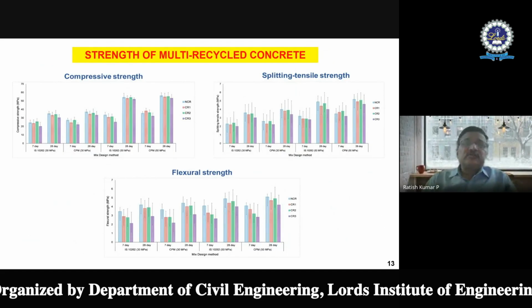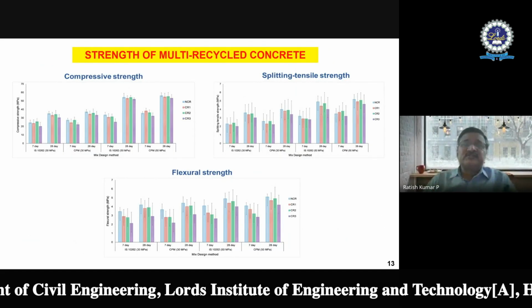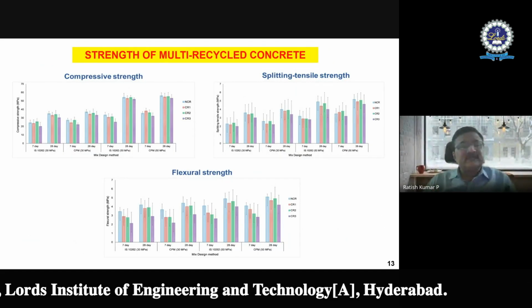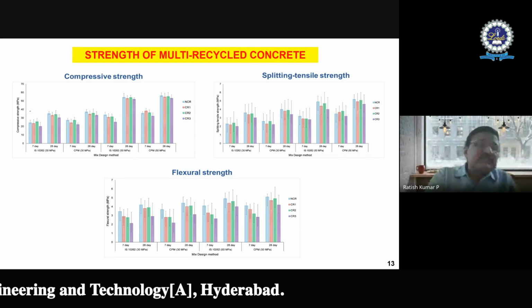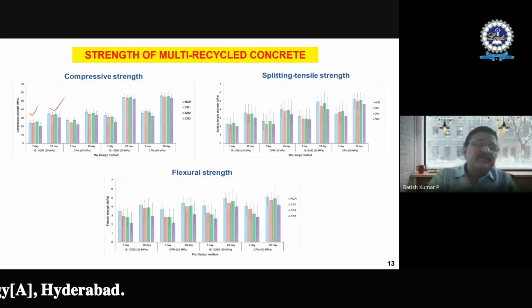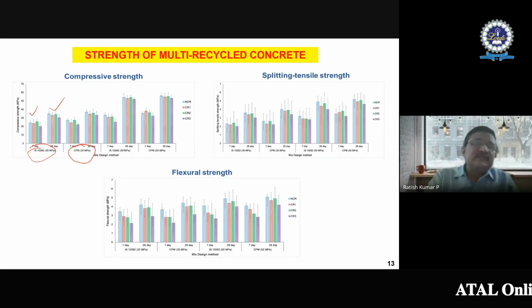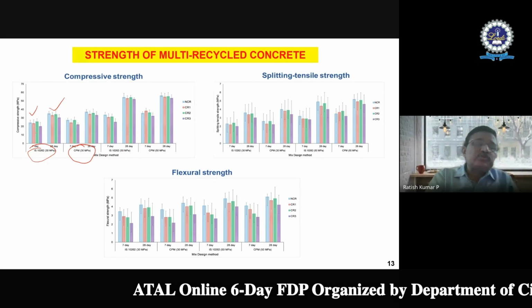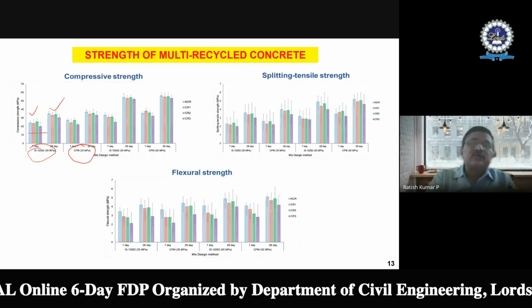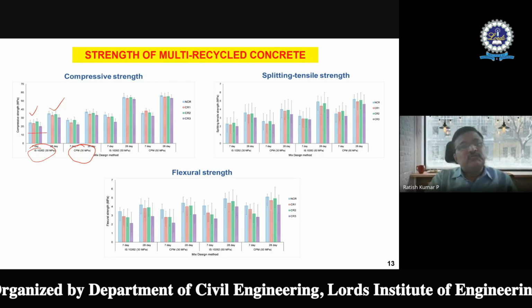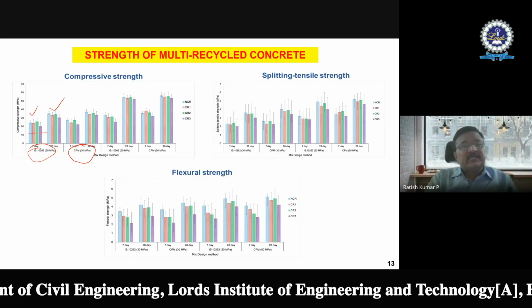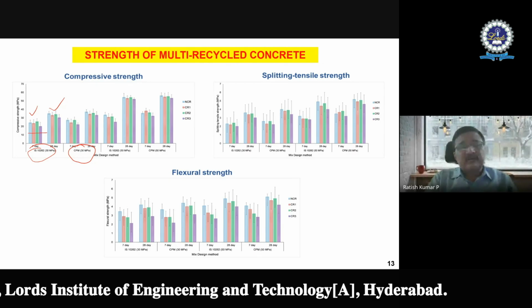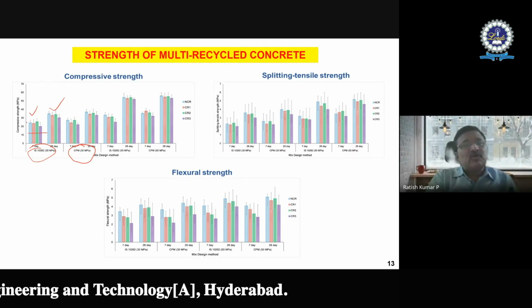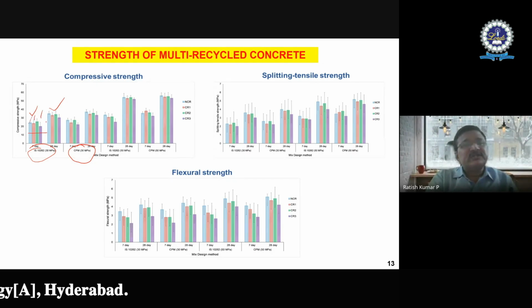Now, let me also give some figures as far as the compressive strength, split tensile strength and flexural strength are concerned. I'm showing here the 7-day strength and the 28-day strength. This is from the IS code method. This is the CPM method. Here I'm comparing the different grades of concrete, shown in the four figures. The light blue one, the orange one, the green one and the violet one correspond to the conventional concrete, the first generation, the second generation, and the third generation.